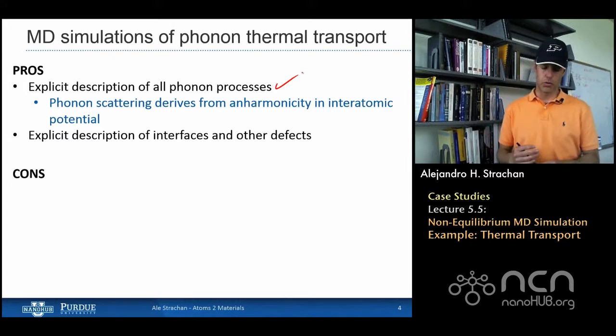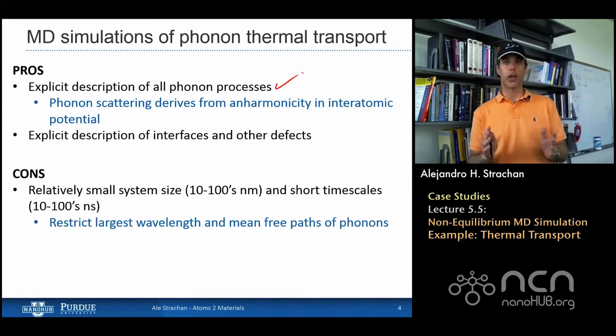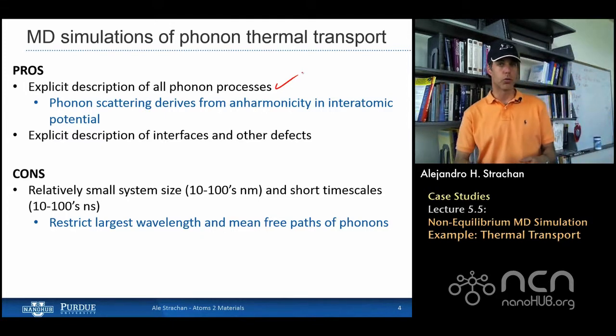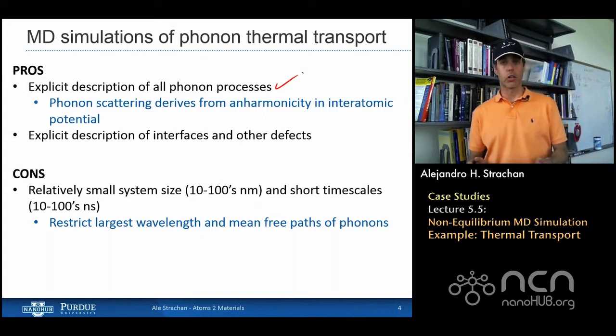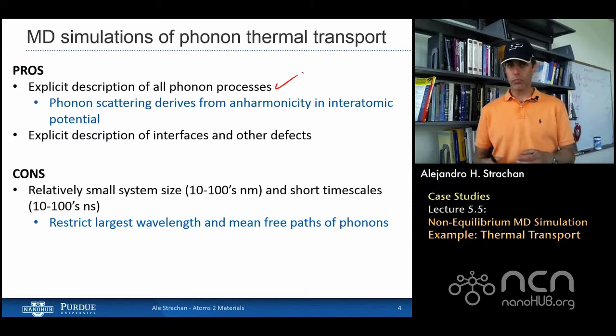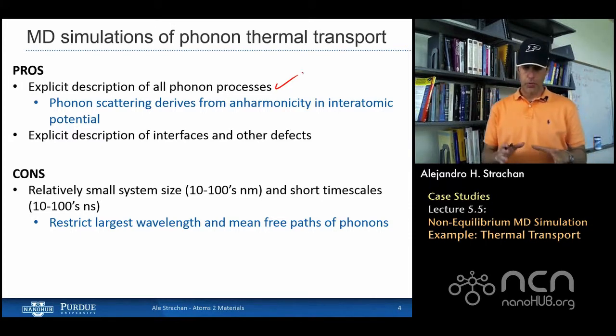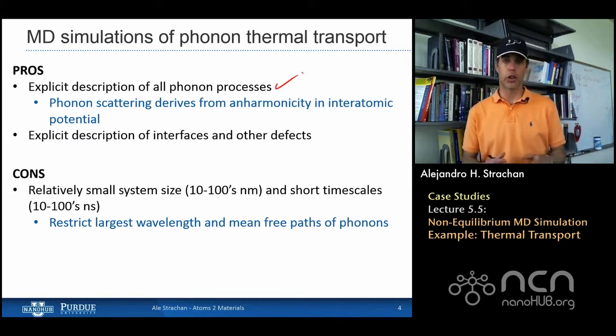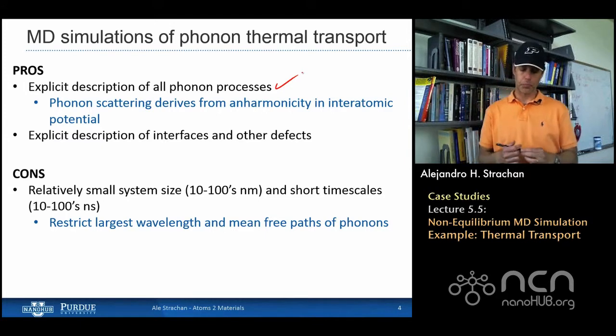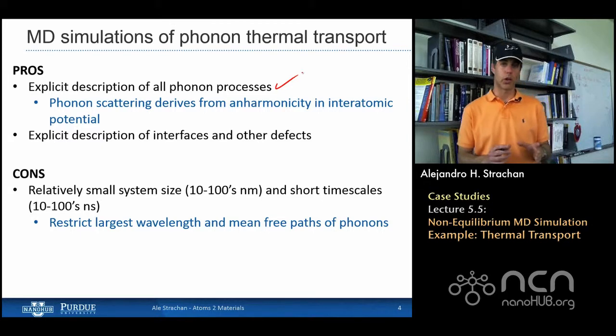There are some cons to doing molecular dynamics simulations. One is that these are expensive simulations, okay? So regarding system size, we're restricted to tens to hundreds of nanometers. In timescales, we're restricted to also tens to maybe 100 nanoseconds. So short size and timescales. And this, of course, restricts the wavelengths of the phonons that we can simulate, and also the mean free paths of the phonons that we can simulate. So that has to be taken into account, and one has to understand the results that one gets in these